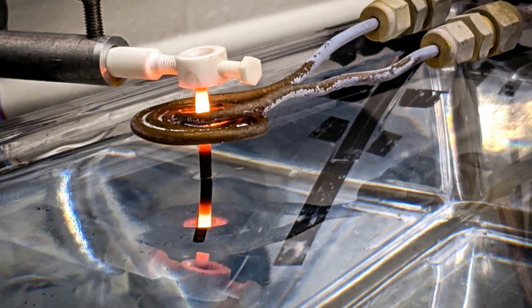After cooling the heat-treated rods, the researchers examined their microstructure using optical and electron microscopy and found that the material's printed microscopic grains were replaced with columnar grains or long crystal-like regions that were significantly larger than the original grains. The team also showed they could manipulate the draw speed and temperature of the rod samples to tailor the material's growing grains, creating regions of specific grain size and orientation. This level of control can enable manufacturers to print turbine blades with site-specific microstructures that are resilient to specific operating conditions.